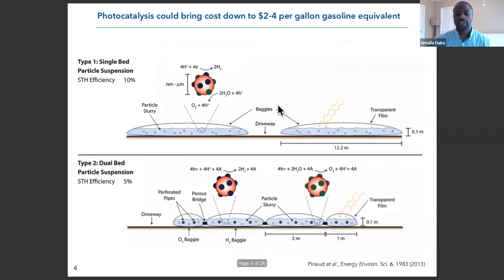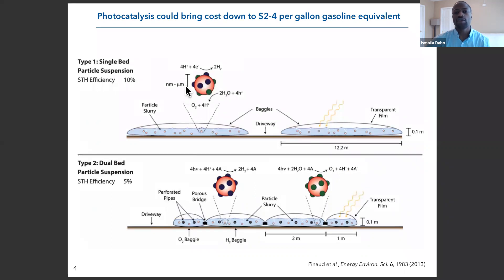One way to address this is through photocatalysis. There are two main concepts of photocatalytic processes to produce hydrogen. The first involves large baggies — bags on the order of 10 meters — containing suspensions of photocatalytic particles that can absorb light. One component on the nanometer-to-micrometer scale is a water-reducing agent that reduces protons into hydrogen, while on the other side, photocatalytic oxidation of water produces oxygen. This allows sunlight to be absorbed and water to be split into oxygen and H₂.